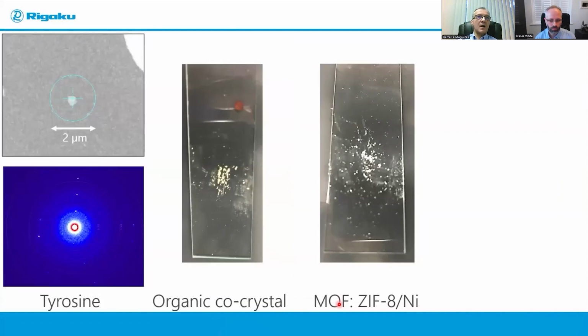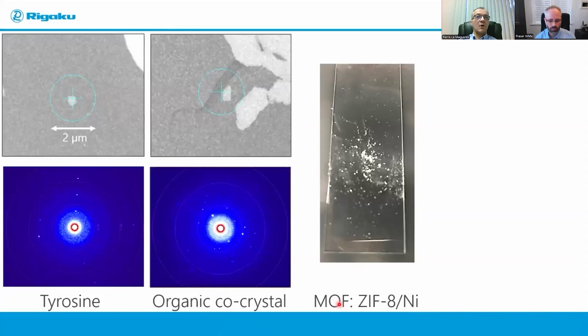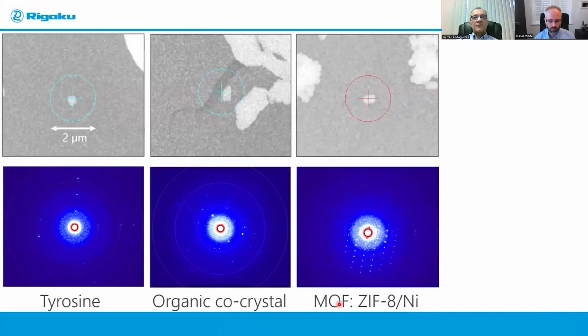Here is the particle of that organic crystal that we used to collect data. See at the top here again a sub half micron particle and a nice diffraction pattern we got out of it. For the ZIF-8 MOF compound, again, we used a particle that was not even as large as half a micron, and you see at the bottom underneath the nice diffraction pattern that we could get from that one particle.